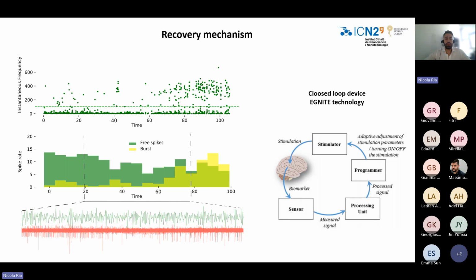This means that the best treatment would involve a closed loop system where the biomarker levels are constantly monitored, and when the biomarker goes above a certain threshold, the current is delivered, and then when the activity is normalized, the current is turned off. This is very important to not have continuous current and to avoid side effects in the brain and battery consumption.